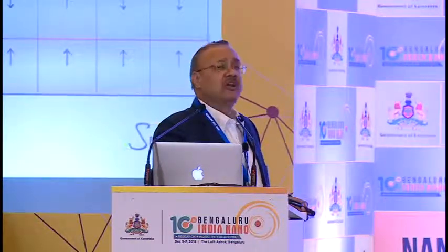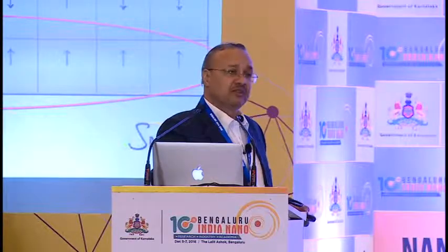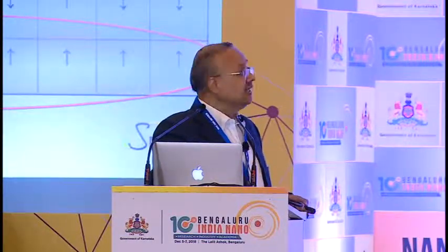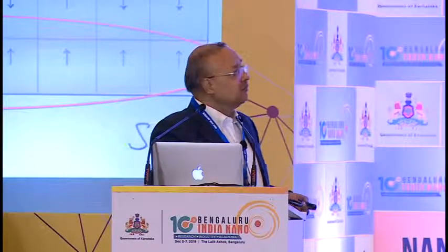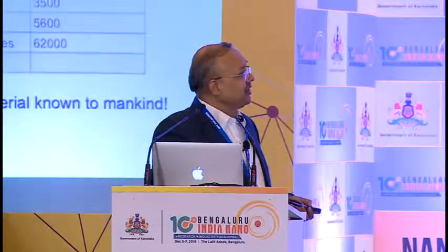If you go to the civil materials, which are concrete, bricks, and composites of these, then again the moduli are very high, but all other strengths are very low except for compression strength. Compression strength is obviously very high because you can build very, very high towers. But when we come to a textile material, it's a different set of properties altogether. All the moduli are extremely low. They're so low that it's very difficult to measure them also, while strength-wise it is very, very high. And only one part, which is compressive strength, is not that great, but all other strengths are quite good. So that makes a unique material.